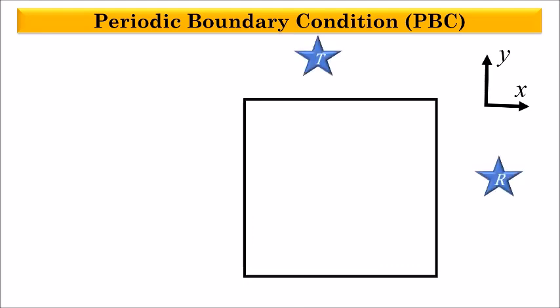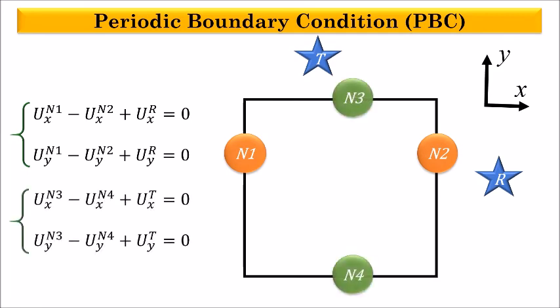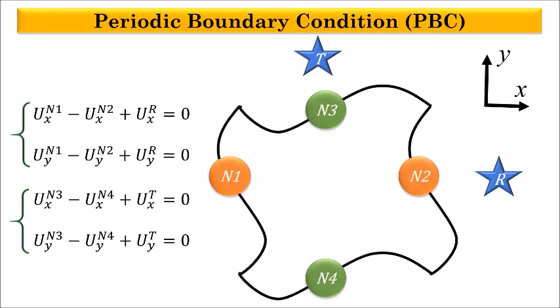To apply periodic boundary conditions, two dummy nodes are defined on the top and right side of the RVE. Next, the nodes on the left and right side of the RVE are connected to the right dummy node through this set of constraint equations. Similarly, the nodes on the top and bottom side of the RVE are connected to the top dummy node through this set of constraint equations. As a result of these constraints, once the temperature is raised, the RVE will deform periodically. As for thermal boundary conditions, we assume a uniform temperature raise that changes linearly with time up to 900 degrees centigrade.